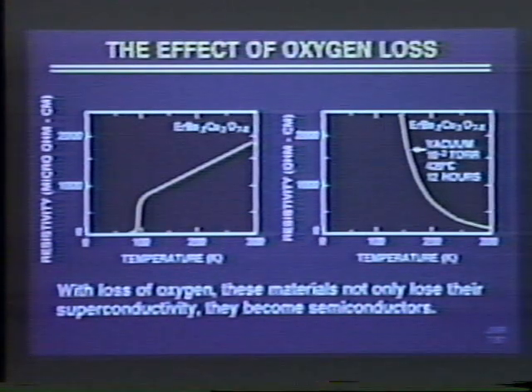On the left, I show a sample, a good bulk sample of 90 degree material, which has a very well-defined transition, a well-defined drop in resistance as you cool the sample down, and has a resistivity measured in microohm centimeters. However, when this sample was heated in vacuum for 12 hours at 400 degrees, a moderate vacuum, this would be a very common step in processing these materials. Or if you didn't know about this problem, it would have been a step you would have assumed you could take. After that heating process, the resistivity is measured in ohm centimeters. The material is a semiconductor, and at low temperatures, it is an insulator.